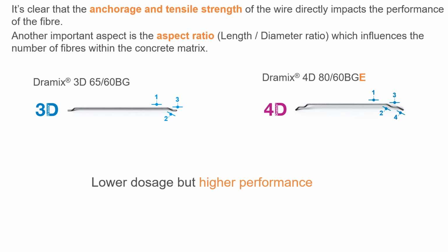Another important aspect is the aspect ratio, which is the length to diameter ratio, which influences the number of fibers within the concrete matrix. For example, with our Dramix 3D 6560 BG fiber, we're getting just over 3,000 fibers per kilo, whereas with our Dramix 4D 8060 BGE fiber, we're getting just under 5,000 fibers per kilo. So we're able to use a lower dosage but higher performance.